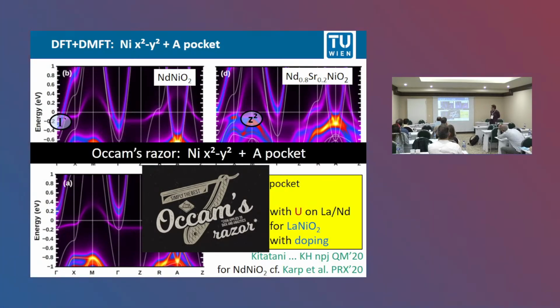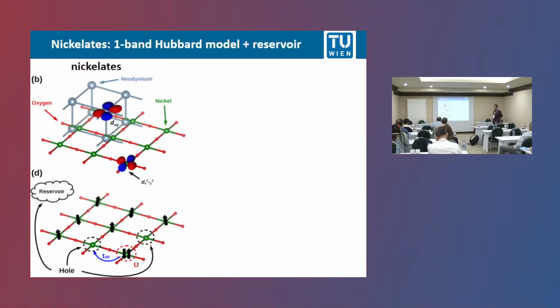And let's use Occam's razor now and make the simplest possible description for the nickelates, and that is just using these two orbitals. It becomes even more simple, because these are the x²−y² orbital in the nickel oxygen 2 plane, and the neodymium xy orbital. And these two orbitals by symmetry don't hybridize.